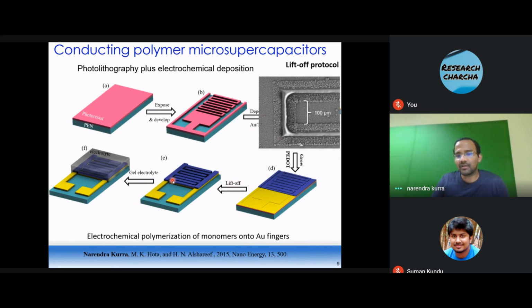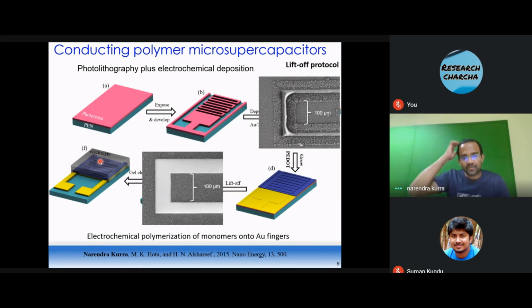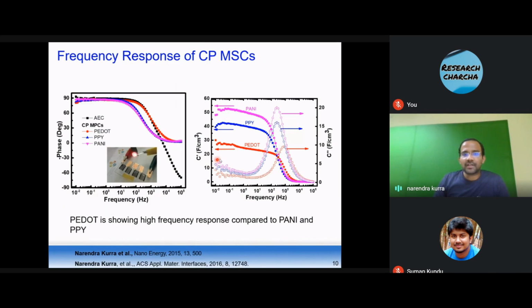Then we got clean, nice fingers of conducting polymer interdigitated electrodes, followed by placing the gel electrolyte. You can see, when you do lift off at this stage after the electrodeposition of conducting polymer, there is no extraneous growth at the edges of the fingers. It's only on top of the gold fingers. This avoids shorting of the fingers and enables successful fabrication of micro supercapacitors. And this technique was employed to check the frequency response of conducting polymer based micro supercapacitors.